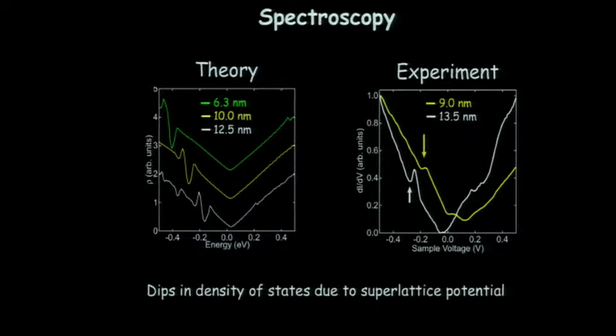And so these are calculations for 6, 10, 12 nanometer Moiré patterns. The density of states, instead of being nicely V-shaped, gets these new dips here from the superlattice. And so this was calculations. And then we went and did some experiments here on a couple different wavelengths. And we see this same dip here in the density of states.